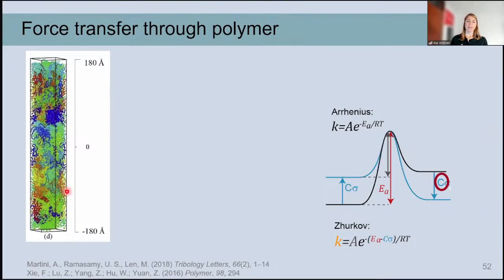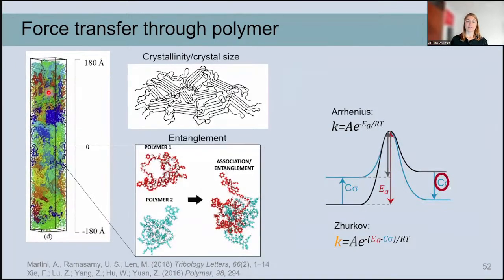So if we have this entangled material with all these different polymers here in different colors, and we basically hit this from the top, then there are a lot of properties of the polymer which can actually influence how well this force arrives at single bonds. So there can be a different crystallinity degree, but there can also be different crystal sizes. So you can see here polymer that is very ordered. So these are crystals, and then in between you have more loosely entangled polymers, or also the degree to which how spaghetti-like the material is in the amorphous region, so how entangled and intertwined the polymers are, can also influence how the force is transferred through the macroscopic piece of polymer.